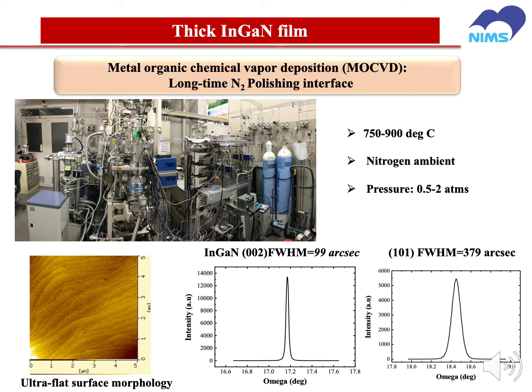Here is the indium gallium nitride obtained using our MOCVD. From the surface morphology we can observe very good atomic steps, which indicate an ultraflat surface. This is the XRD rocking curve showing the quality of the indium gallium nitride material. We can see the full width at half maximum for the InGaN 002 plane from XRD is only 99 arcseconds. This is the lowest value ever reported for indium gallium nitride. And for the 101 plane, the FWHM value is also very good.